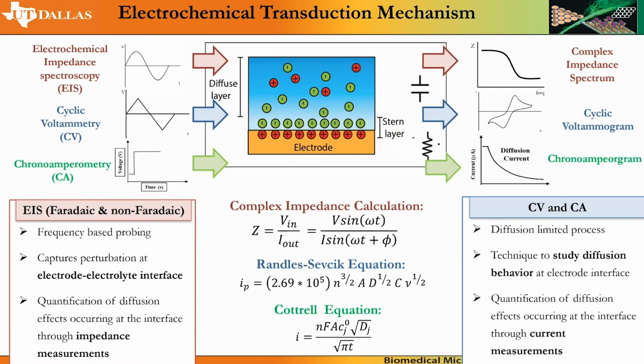So for the electrochemical transduction mechanism, the electrochemical techniques we'll be using to cross-validate our results are firstly electrochemical impedance spectroscopy, cyclic voltammetry, and chronoamperometry. All of these techniques we'll be using to monitor the electrode-electrolyte interface. What is the electrode-electrolyte interface? It is the area where your particles or VOCs diffuse. You can see this is the diffuse layer that's present, and it causes a change in the Stern layer such that you can actually see a change in signal response. EIS can be both Faradaic and non-Faradaic in nature.